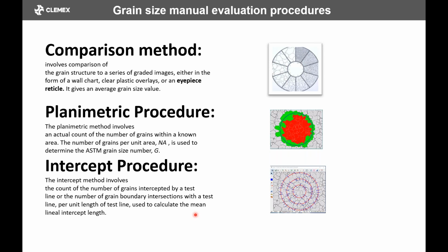So there are 3 major methods. The comparison method is pretty straightforward, and I'm sure everybody's familiar with that. Basically you look at a comparative reference. In this case, this is something you would look at in the eyepieces and you would see the individual grain size, and then you look at the live image underneath, and then you say, well, it's 4, 5, or 5.5, whatever. But there are also other methods where we can use charts rather than only the eyepieces. The planimetric procedure means that we're counting the number of grains within a known area. That's why we have a circle, and we'll go over that later on. And then the intercept procedure, which is probably the most accurate one, is where we count the intercepts touching a line. There are various approaches to that.